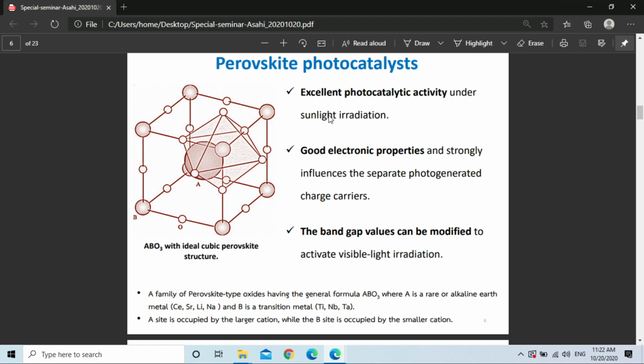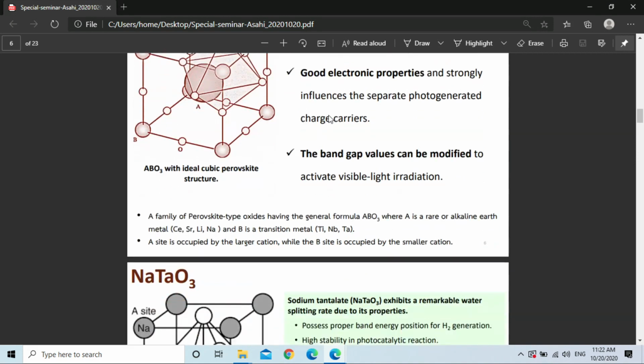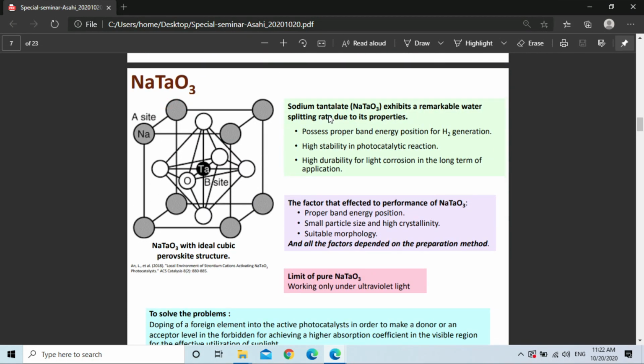This type of semiconductor has excellent photocatalytic activity and good electronic properties, and the band gap of this material can be easily modified by doping with some metal ion so that it can be activated under visible light. Among various perovskite structures, sodium tantalate is one of the materials that was reported. This material has superior properties over other semiconductors, in that it has a high positive potential for hydrogen production, very high stability after photoreaction, and high stability against light corrosion.